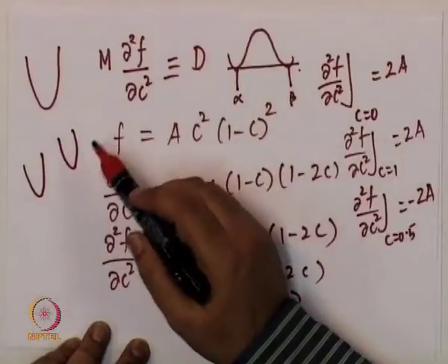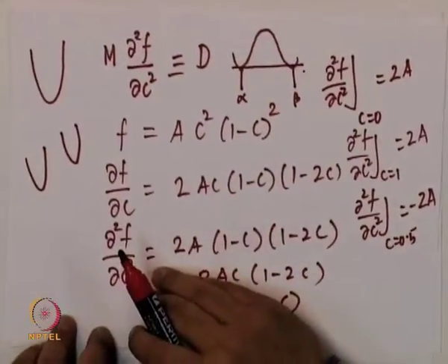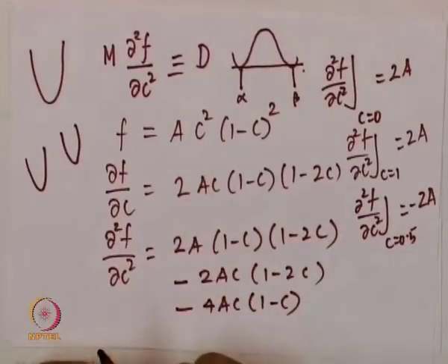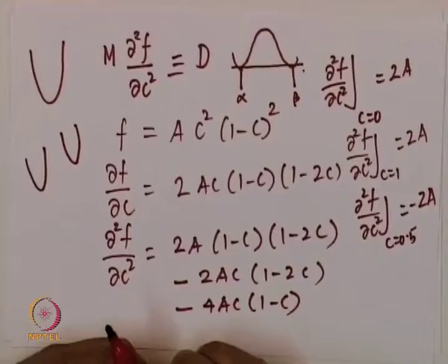One of the ways in which you can achieve this kind of free energy curve is by taking two such free energy curves and connecting them through the second order parameter, that is the phi order parameter. I am going to show you exactly how this is done, but this is one of the reasons why you might want to use more than one order parameter. In this scenario, we will choose the f appropriately so that the diffusivity remains constant. So, we have a system in which the diffusivity is constant. We can compare the results with Zener and Frank in one dimension, because there is no Gibbs-Thompson effect in their model, and it is true in our numerical simulation also.